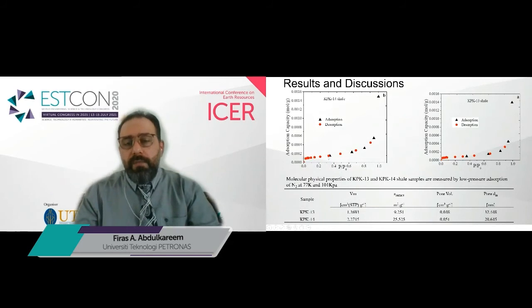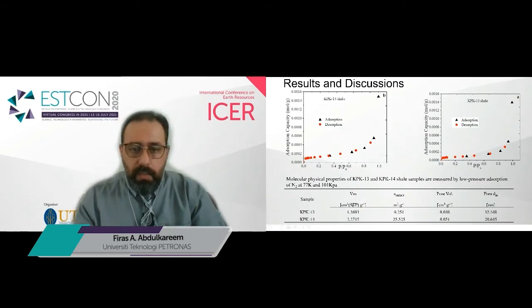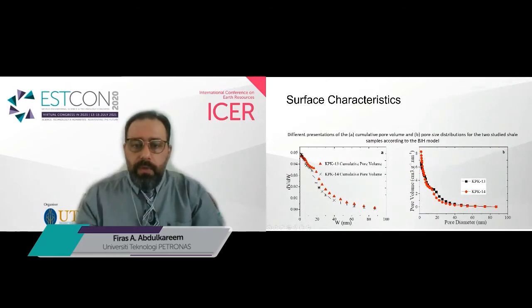On the surface physical characteristics of the shale, we can see that the samples showed more or less double the molecular volume of the pores on KPK14 compared to the KPK13, and a much higher surface area as well, compared to a much higher pore diameter on KPK13 compared to the KPK14. This might refer to an easier penetration or flow of the solvent during the extraction process, which can be analyzed later. On the same side, the pore distribution shows a high percentage of pores within the micropore region compared to the meso and macro regions on both samples.